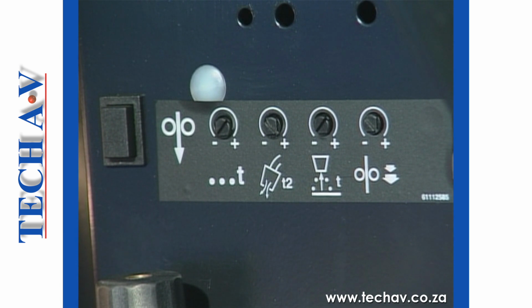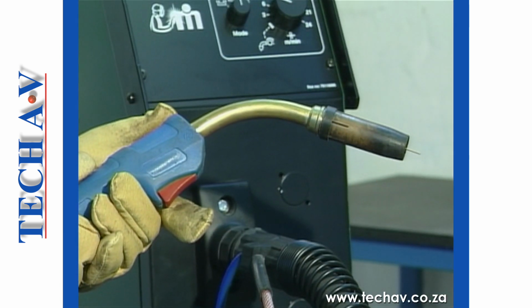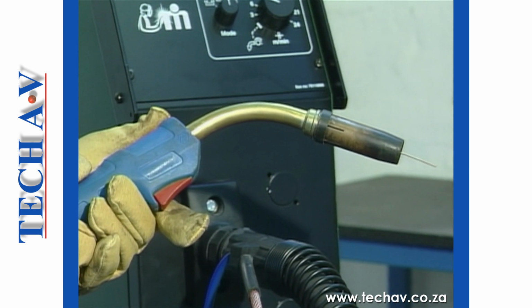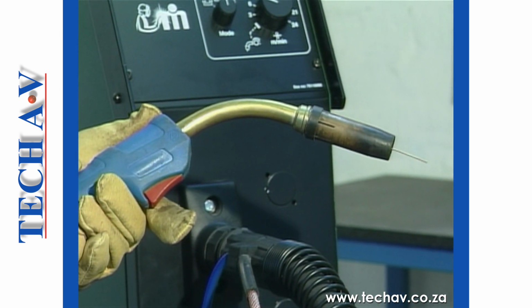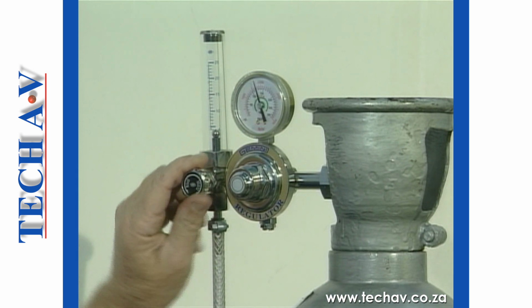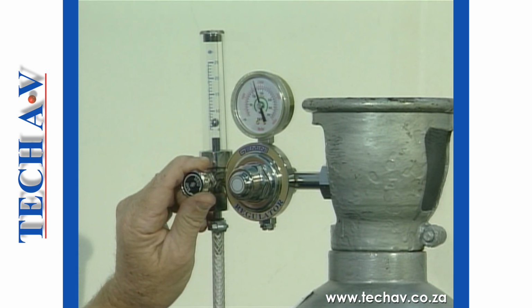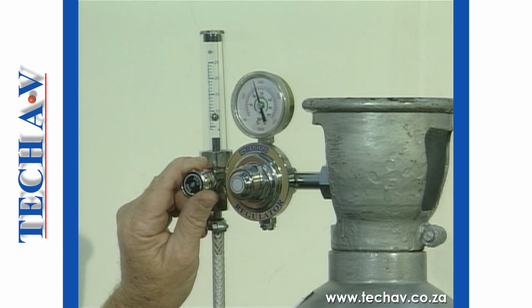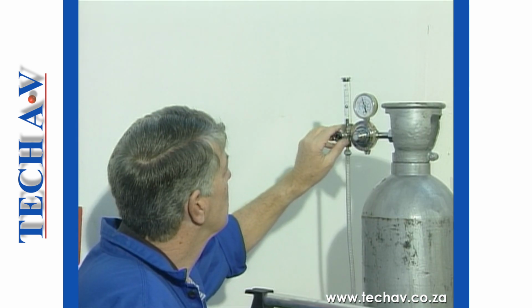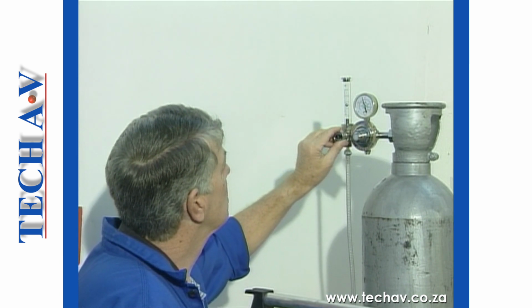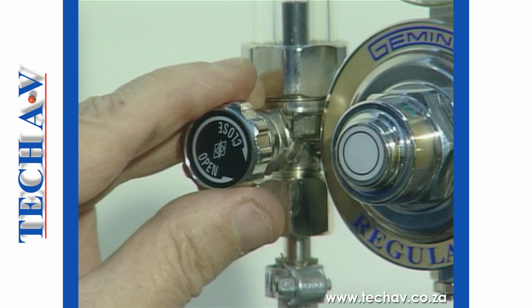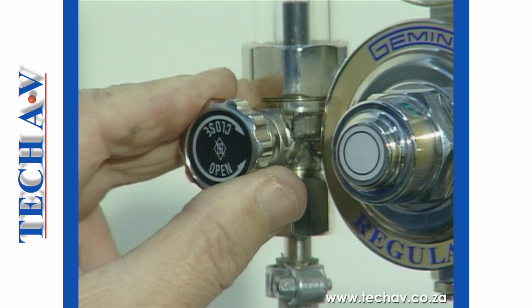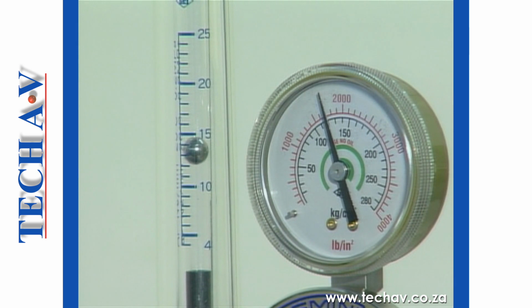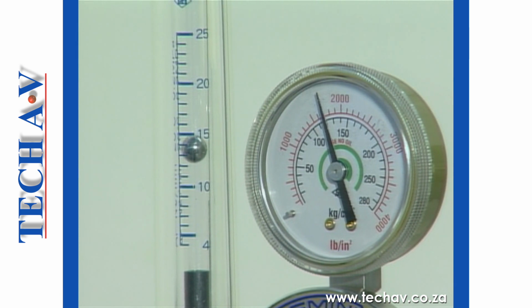Next, press the purge button, or operate the gun trigger momentarily in order to activate the gas control valve within the welding machine. The flow control valve is now slowly opened, and the indicator ball will rise inside the sight tube. Observe the top of the ball at eye level and compare this position to the graduated scale on the tube. Adjust the flow by manipulating the control valve until the desired flow rate has been achieved. When using an argon mix gas, the flow rate is normally set between 12 and 15 liters per minute.